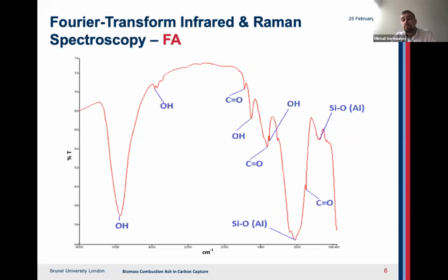Apart from that, the double bond between the C and oxygen present in the carbonyl group has been identified. This functional group, however, is not exclusive to organic materials and can be seen in the carbonates that are proposed to exist in our biomass combustion ash. Furthermore, silicon-oxygen bonds were also identified within the FA.